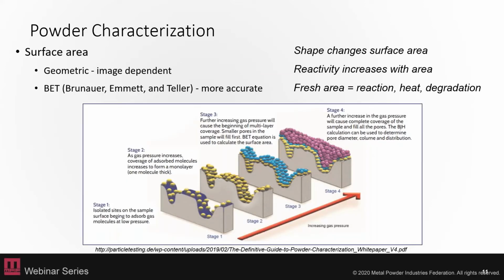So then not just the internal features, but also, again, we've talked a lot about the surfaces of these powders, as powders are a large surface area material. There are surface area measurements that are geometric, which are just image dependent, but you can also do BET, which is more accurate, and that's shown on the bottom: you're doing gas deposition on the surfaces and getting monolayers, and then filling in your surface pores to get your full surface area measurement through increasing pressures.